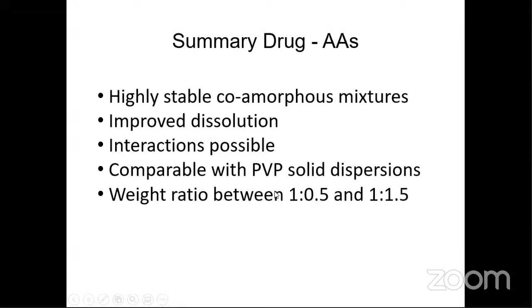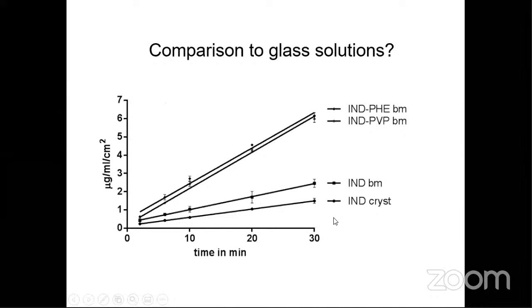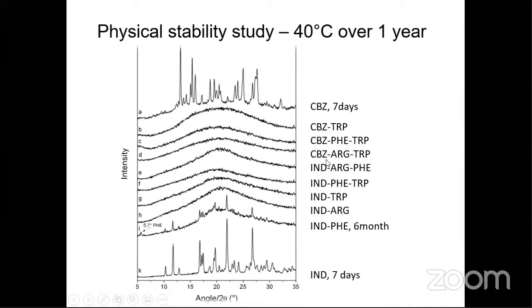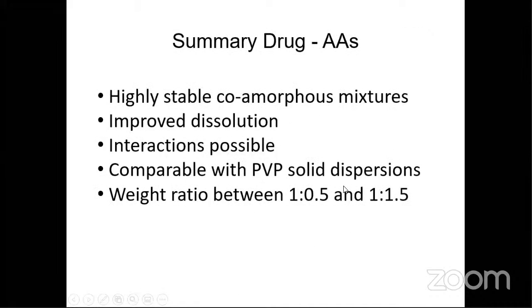Let's get a summary. Highly stable co-amorphous mixtures improve dissolution, and it is comparable with PVP solid dispersions. The weight ratio is very important across different ratios. Usually, if we want the highest physical stability, we use a 1-to-1 molar ratio, or 1-to-1-to-1. This is the most stable.